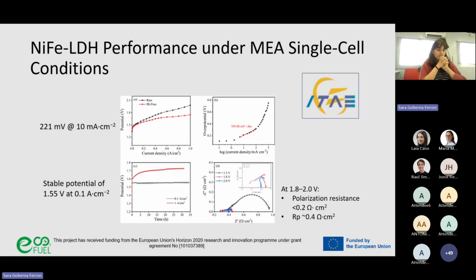This performance is well in line with what is typically reported for nickel iron-based oxygen evolution catalysts, especially considering the simplicity and the sustainability of the solvent-free synthetic method. Now, regarding the stability or the durability of the catalyst, we operated the cell at a constant current density of 0.1 amps per square centimeter for 35 hours. And as you can see, the cell voltage remains stable around 1.5 volts. This indicates a good operational stability under sustained oxygen evolution conditions.